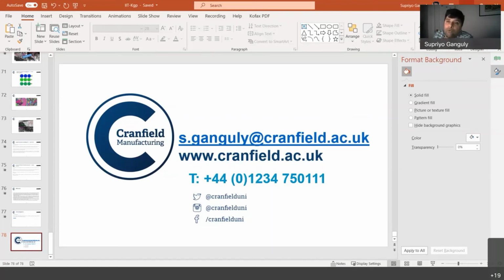that is, how to control the cooling rate of a deposit. I've just been the internal examiner of a student called Alex. So he actually did some really good work. So what is happening now, we are trying to use wavelength corrected pyrometers to measure accurately the weld pool temperature, and from there we're trying to control the deposit parameters. As I said in the beginning, plasma and TIG are two processes where the wire feeding and the current are independently controlled. They are not coupled.